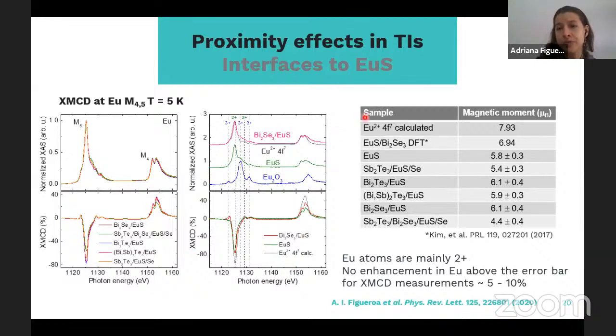And then by analysis of the magneto-optical sum rules, we were able to extract the magnetic moment of the europium for all these samples, and then we compared with what is calculated for a europium 2+ spectra, and also what is reported for DFT calculations, and we found no enhancement of the magnetic moment, or at least not above the error bar for XMCD measurements.